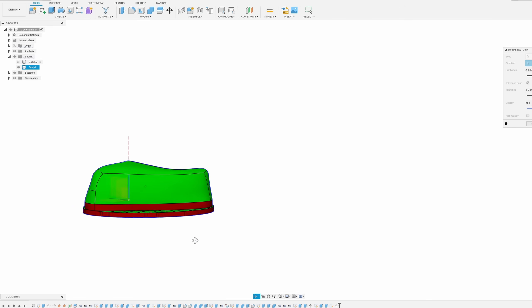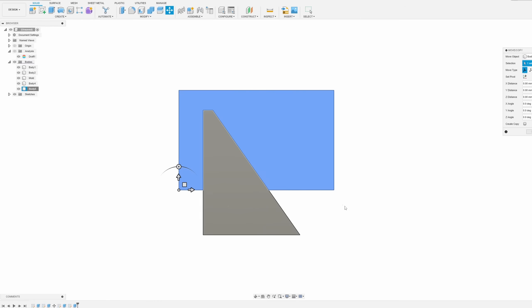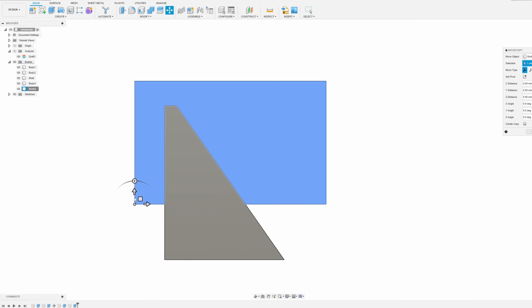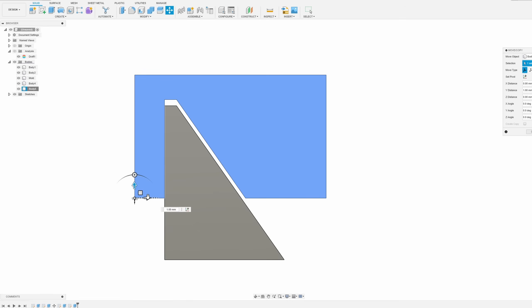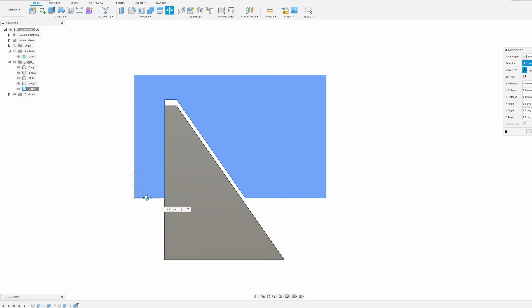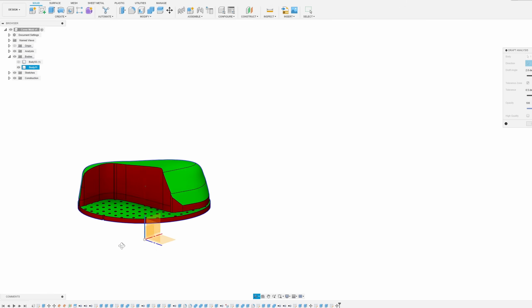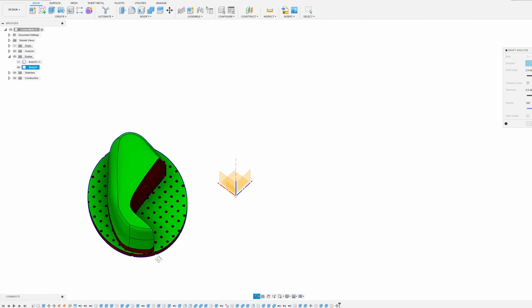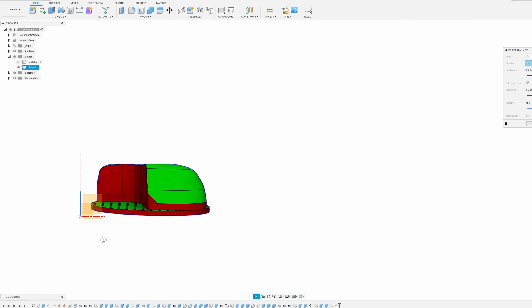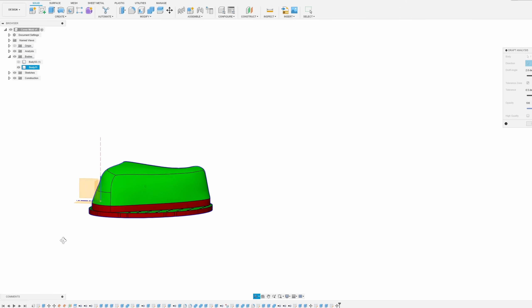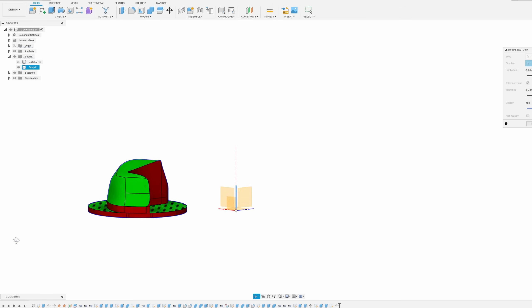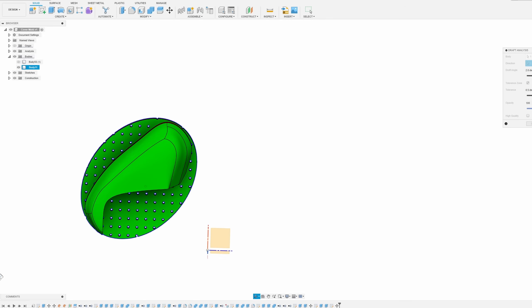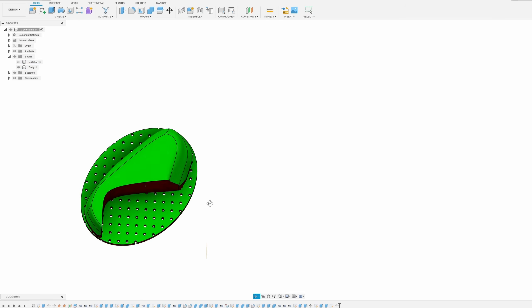Although in some cases, vacuum molds will release if enough pressure can be released from those vertical faces as well. Essentially, two opposing 90 degree walls are harder to release than only one 90 degree wall. Beyond that one problem face, I believe the mold will work fine. I also added an array of holes to the base to help vacuum all the air from the underside of the plastic and help give the part the best chance of working.